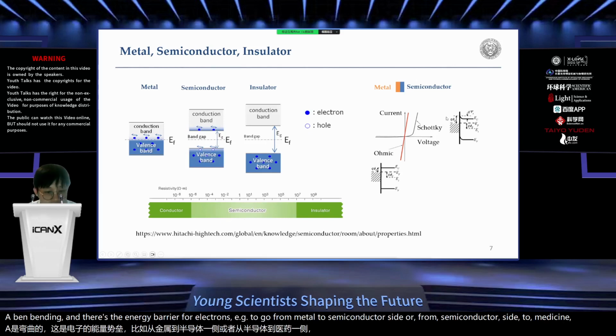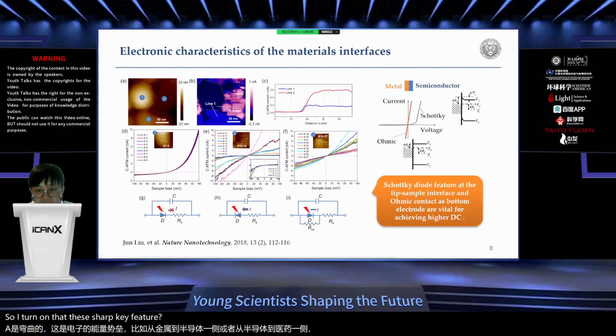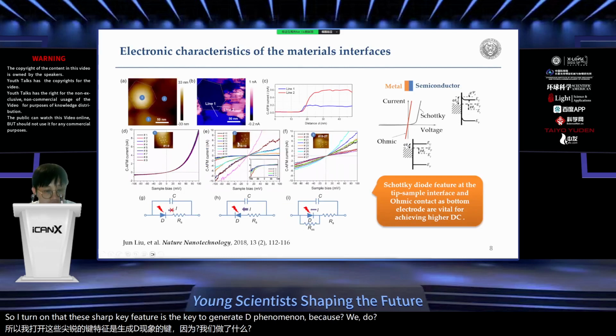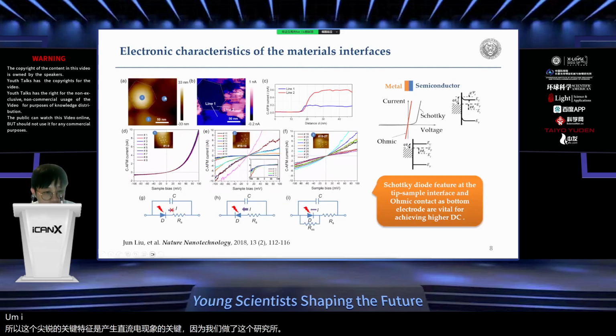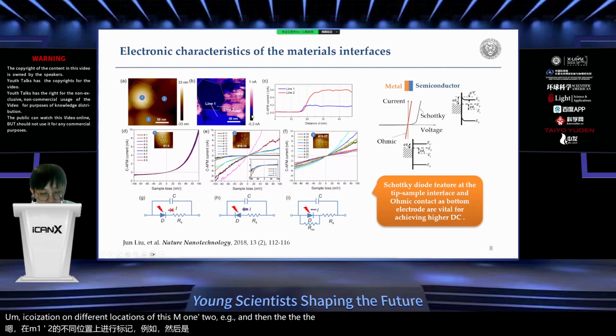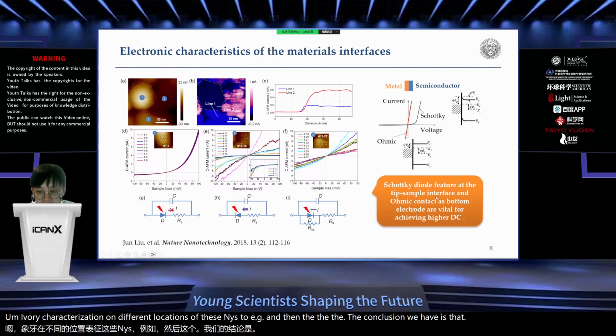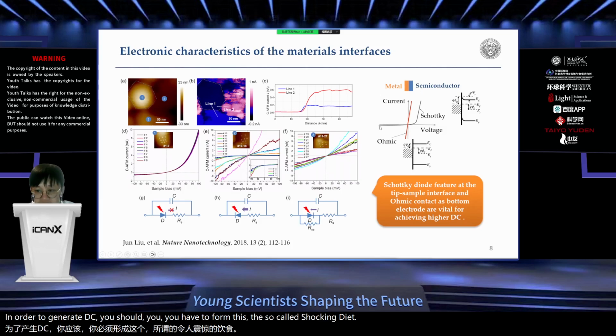So it turned out that this Schottky feature is the key to generating the DC phenomenon, because we did in situ IV characterization on different locations of this MoS2, for example. And then the conclusion we have is that in order to generate DC, you have to form the so-called Schottky diode, right, with these rectifying features in order to generate this phenomenon.